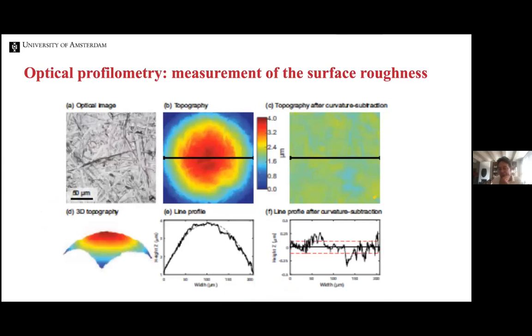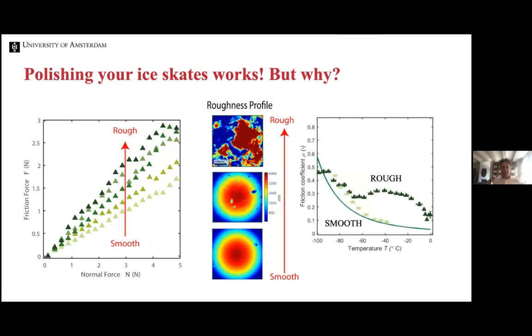So we tried to quantify this. We used optical profilometry to actually determine the roughness. We subtract the curvature of the sphere, and then we get some roughness profile that we can characterize by its root mean square. And then we can see two things. One, the Arrhenius behavior actually disappears or becomes attenuated, if you like. And the second is that close to melting, it actually is very difficult to skate if you have a rough skate.